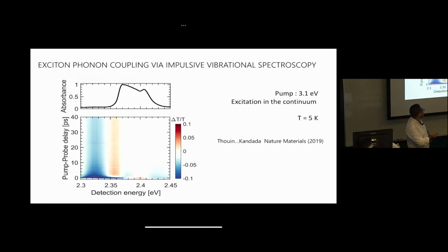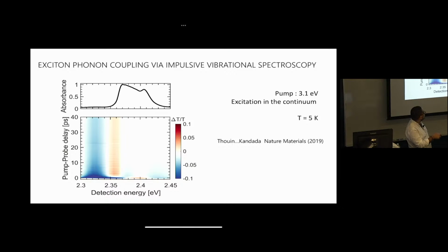a transient absorption spectrum. Here we have your ground state absorption spectrum. This is at 5 Kelvin. And you pump the photocarrier, so you pump at high energy. You're injecting electrons into the conduction band. You're not exciting the excitons resonantly yet, but you're just injecting electrons in the conduction band. And you get here in the region of your ground state exciton absorption this transient transmission spectrum. And it's complex because you pump, you move electrons from valence band to conduction band. There are changes in the permittivity function and so on. You get shifts, and you get a complex line shape. And so at the moment, let's not worry about that.